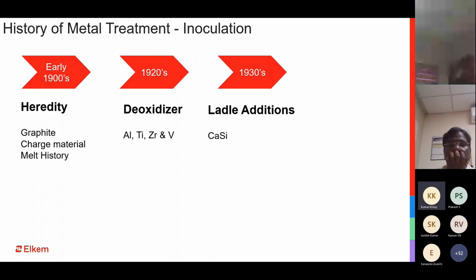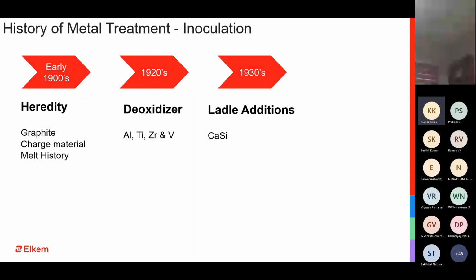About 10-15 years later, in the 1930s, we had calcium silicide as the additive into the ladle. So the concept of adding something to the ladle more as a post treatment, not in the furnace, was done for the first time around the 1930s. And the first material which was used as a ladle addition with the aim to modify or improve the quality of the metal was calcium silicide. After the 1930s, once the concept of treating the liquid metal with some additives after the furnace came into the picture, there was a series of inventions which brought about many of the inoculating elements. Some of it, in fact most of it, we see even today.